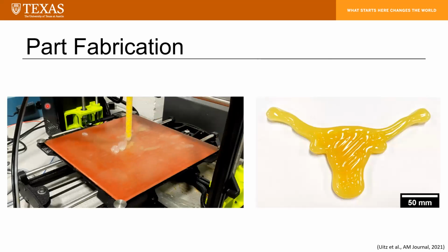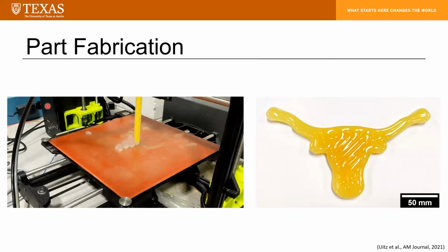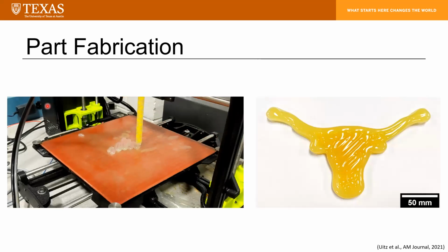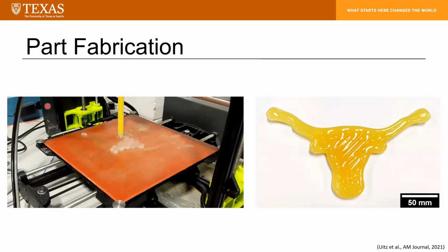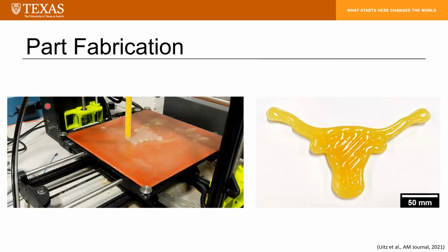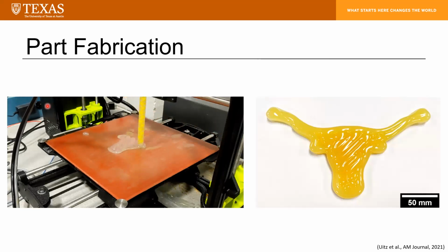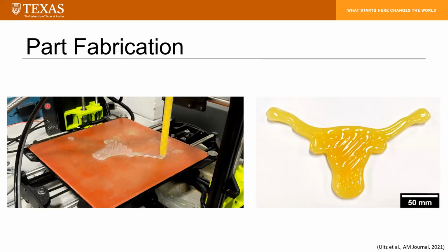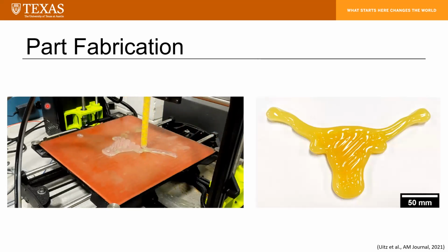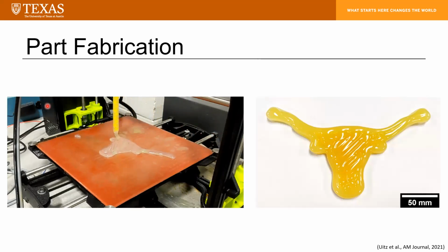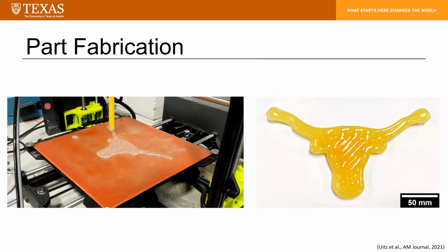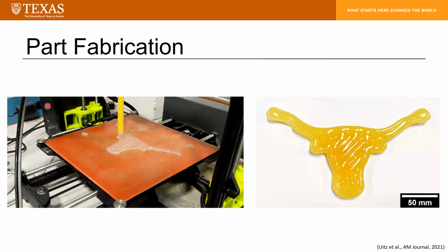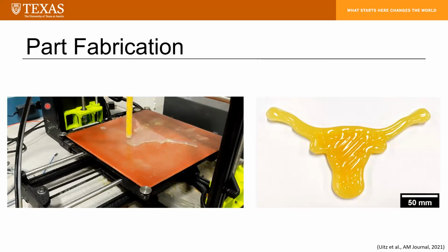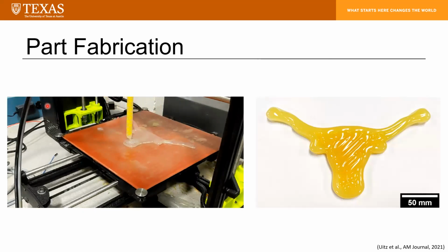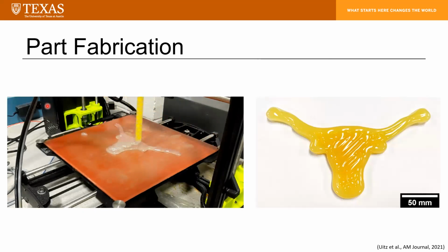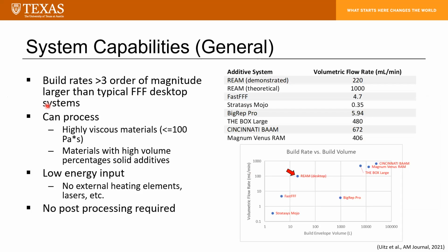Here is the desktop system in action. We're printing a Longhorn, which is approximately 200 millimeters from horn tip to horn tip, layer height of 2.5 millimeters. And you can see we're almost done with the first layer already. This is a very quick process. The material that we're printing with is a densely cross-linked epoxy. Just for your edification there.